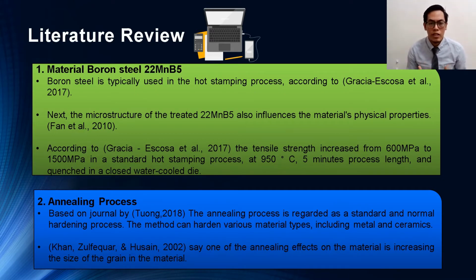For the material boron steel 22MnB5, Garcia-Escosa says boron steel is typically used in the hot stamping process. Next, the microstructure of treated 22MnB5 also influences the material's physical properties, as said by Fan. According to Garcia-Escosa 2017, the tensile strength increased from 600 MPa to 1500 MPa in a standard hot stamping process at 950 degrees Celsius, with a 5-minute process length and a quench in a closed water-cooled die.